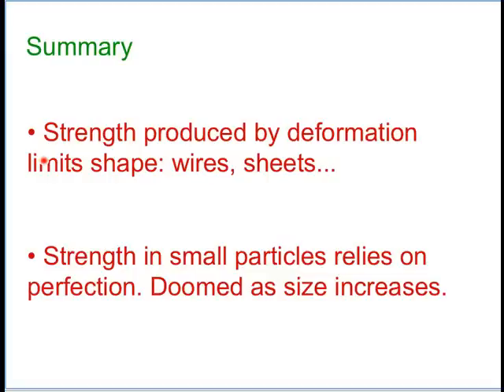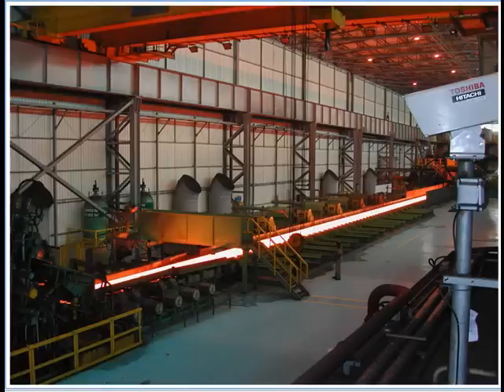And microalloying means introducing very small concentrations of, for example, niobium in the steel, which forms niobium carbides and stops the grains from growing. And the small concentration is as small as 0.02%. And that led to a revolution in steel technology by thermomechanical processing and a dramatic increase in the strength and toughness of steels, because making the grains smaller both increases strength and the toughness.